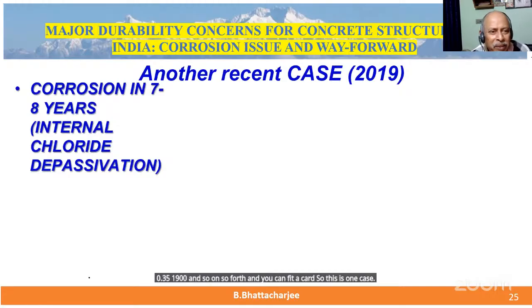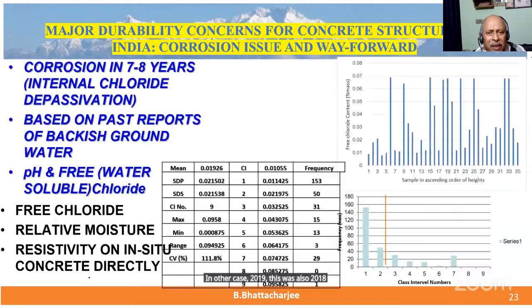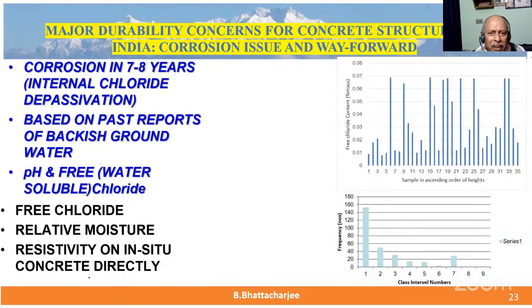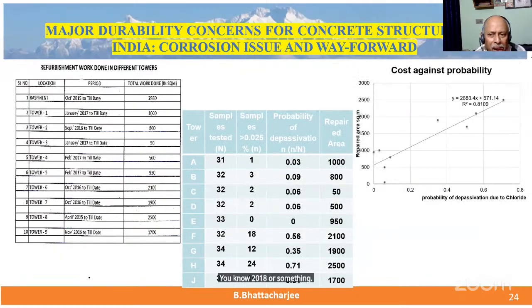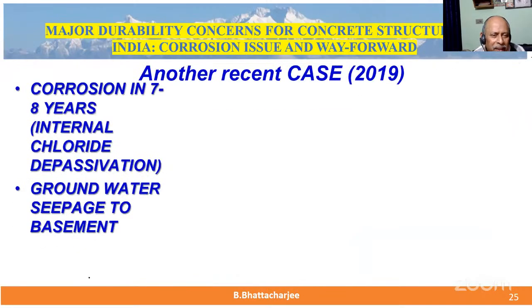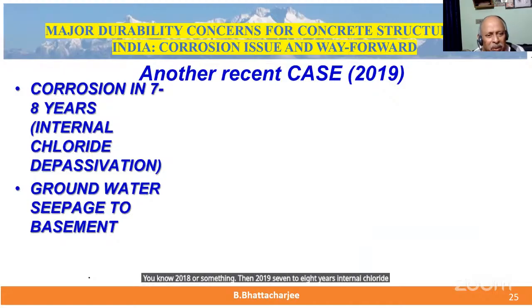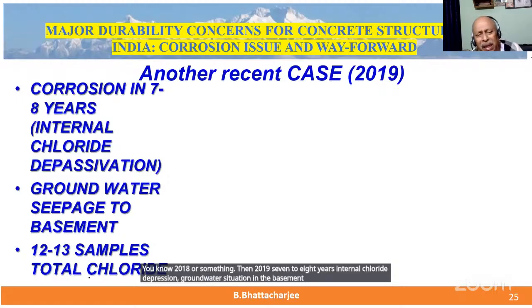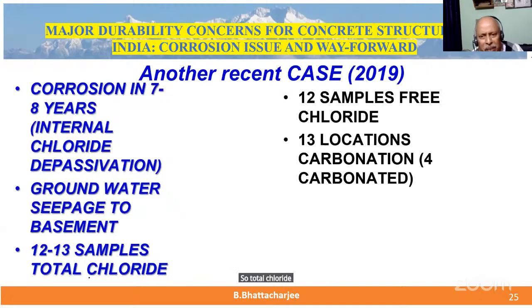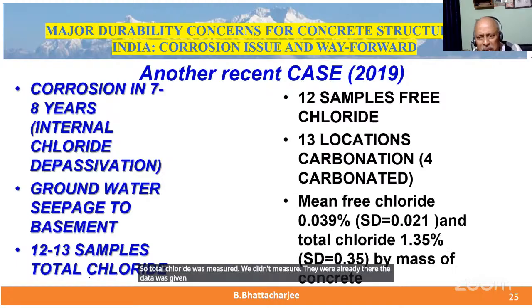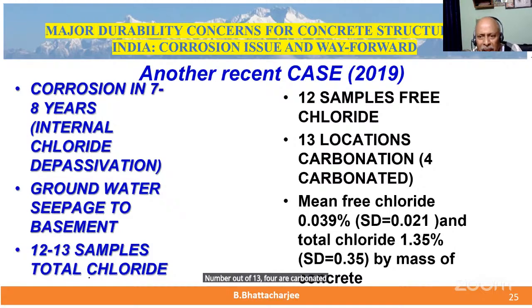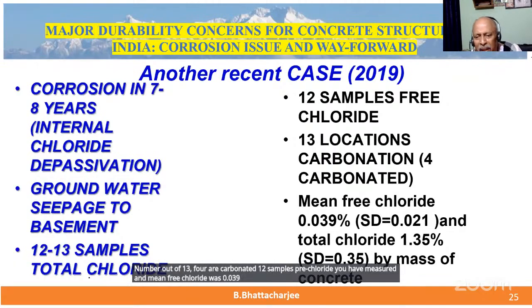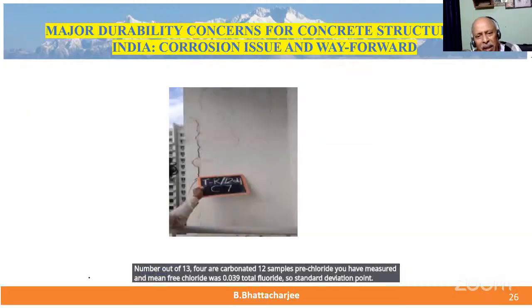Another case, 2019. This was also 2018, I think, or something like that. Then 2019, 7 to 8 years internal chloride depassivation, groundwater seepage in the basement, because we couldn't do the detailed analysis there, but it is there all over the place actually. So total chloride was measured. We didn't measure, they were already there, the data was given. Carbonation was measured, 4 number. Out of 13, 4 were carbonated. 12 samples, free chloride was measured, and mean free chloride was 0.039, total chloride, so standard deviation 0.35, etc., and so on.